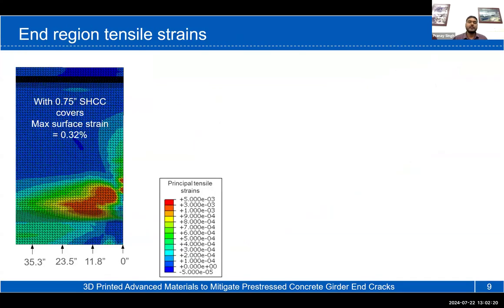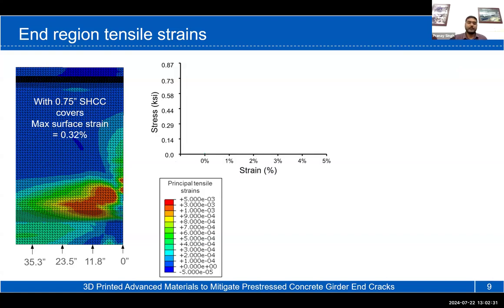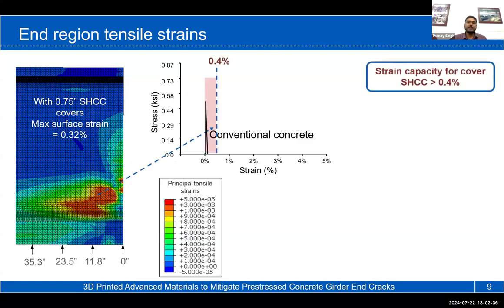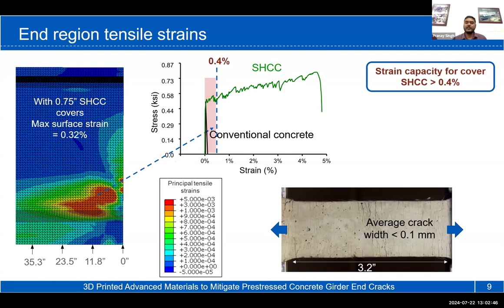So when we did the numerical simulation, we obtained that the maximum strain that is reached on the cover surface is somewhere at 0.32%. And this marks the limit for the strain capacity that we will want to have with our covers. So as we can see in the stress strain plot, a conventional concrete will actually get significant cracks at this strain level. However, the strain hardening cementitious composites have the ability to sustain this kind of strain, and the average crack width, even at this strain level, will be somewhere less than 0.1 millimeter.